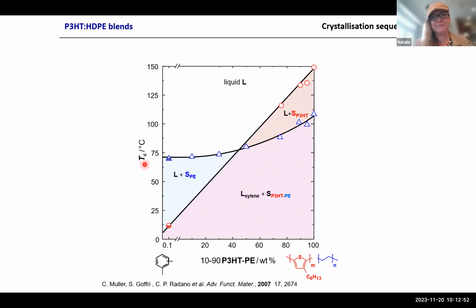One way we do it often is measuring the crystallization temperature in solution. So we measured the crystallization temperature of P3HT in a solvent. Here you see that P3HT has some polarity. So if you add a solvent, it can interact. And therefore, the more solvent you add, the P3HT will crystallize below room temperature. Polyethylene, though, is only carbon and hydrogen. So you see if you add a solvent, the crystallization temperature is just a little reduced from 100-something degrees C to around 75.